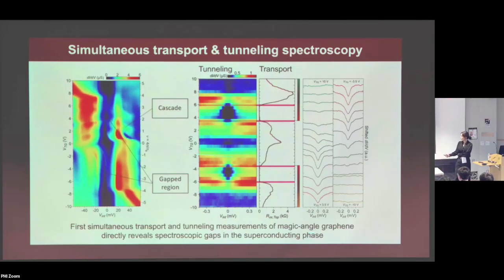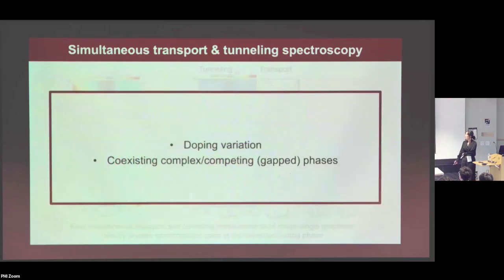So we have achieved the simultaneous transport tunneling measurements of magic angle graphene, where we could directly correlate the spectroscopic gaps with the dissipationless transport phenomena. Okay, so now we can come back to the two original concerns that we had. First concern was that there might be some doping variation, so then the spectroscopic gap, what phase is it corresponding to? Now, with the simultaneous measurement, at least this concern is gone. We could directly see that wherever we see those gaps, whatever they are, they correspond to the superconducting regions. So that concern is gone.